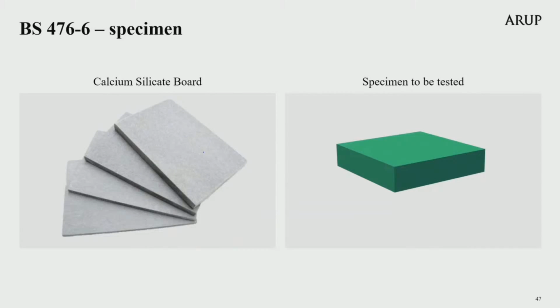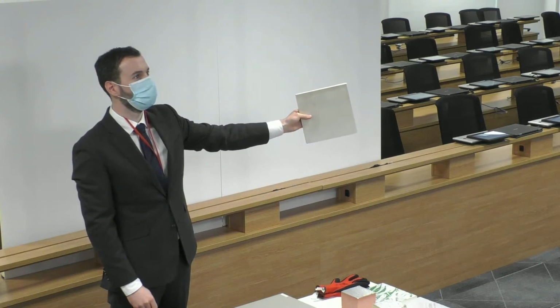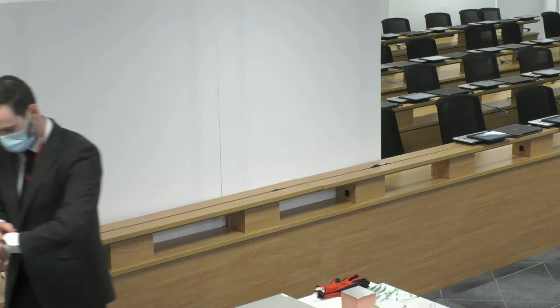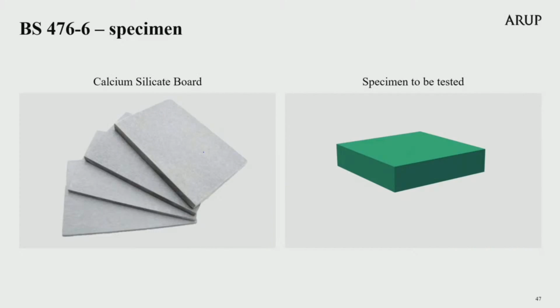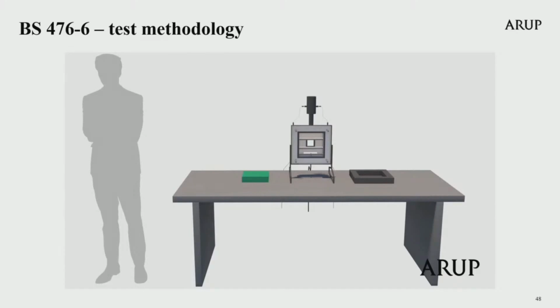This test consists of data measured from two different materials. As well as the specimen to be tested, the test also requires a specimen of calcium silicate to be prepared. Calcium silicate is a non-combustible material, and Tom is now holding up a piece of that board for reference. In its board form, it is used in the test combustion chamber as a benchmark, and the data from the test specimen is then compared to the data obtained when the calcium silicate board is tested first. Only one calcium silicate specimen is required, however, at least 3 of the material specimens must be tested. I will now present a video of this test procedure.